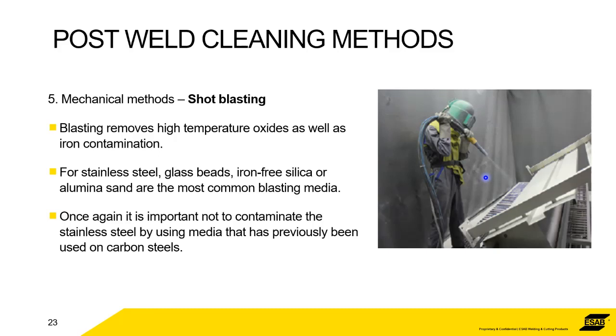And again, if it's a shop that's shot blasting a number of different alloys, then you mustn't use the shot that's been used on carbon steel. Exactly the same. You'll be blasting small particles of iron into the surface of the stainless. Exactly what you don't want. Shot blasting is reasonably common because it's fairly quick.